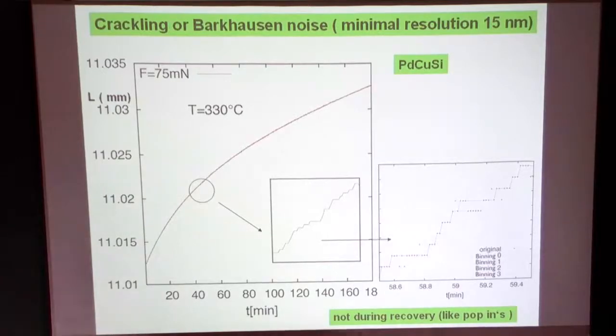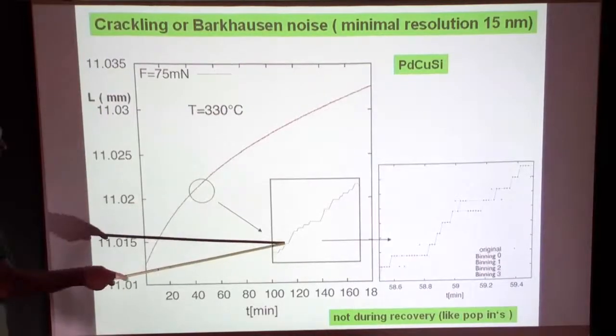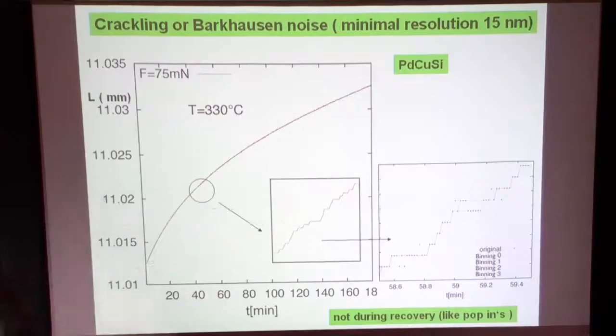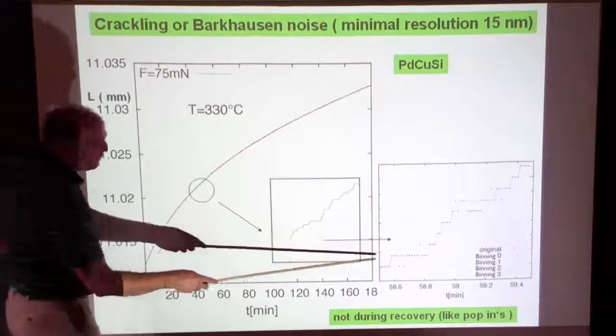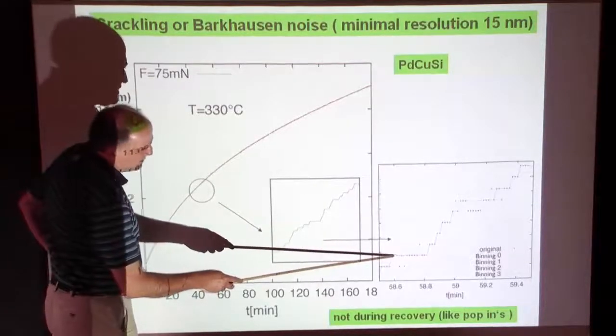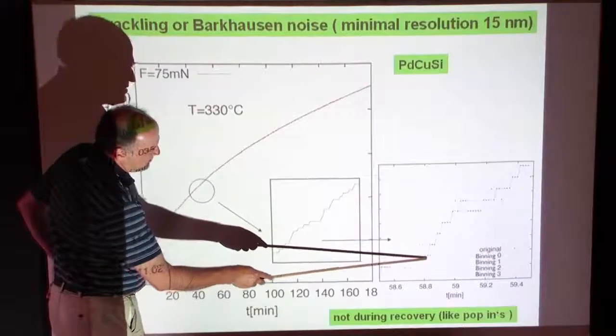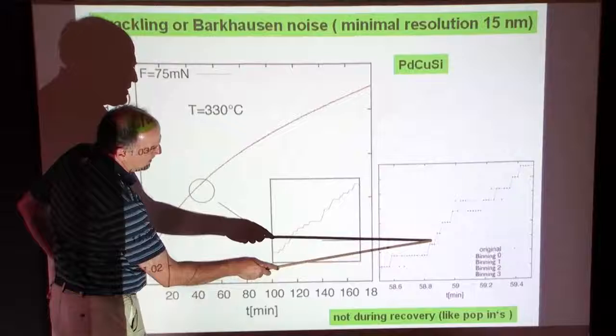So for high resolution, we have tons of data at 15 nanometer resolution, and with the atomic force microscope we were not able to discriminate between noise which comes from the machine itself and noise which comes from the sample. Here we just have a different idea. We don't measure the slip lengths like Kai did in her mean field model. We just wait a certain time until this event happens. So we analyze these waiting times. We have the waiting time for an event, and we say the event takes place if more ups than downs are occurring.